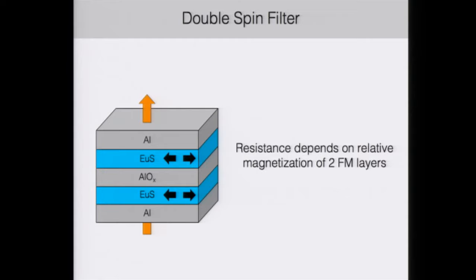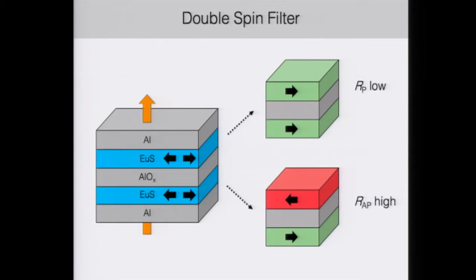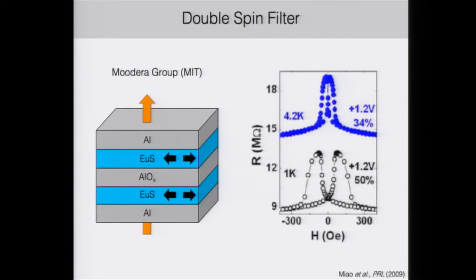You can then take this idea of the spin filter a step further and have a double spin filter magnetic tunnel junction, where the resistance will depend on the relative magnetization of the two magnetic layers in your barrier. And just like with GMR, you'll have a low resistance when the magnetizations are parallel and a high resistance when they're anti-parallel. And this has been pioneered by Jagadish Moodera's group, also at MIT, using europium sulfide layers separated by an aluminum oxide spacer. And you can see that they're able to switch between high and low resistance states by applying an in-plane magnetic field to switch these two magnetizations.